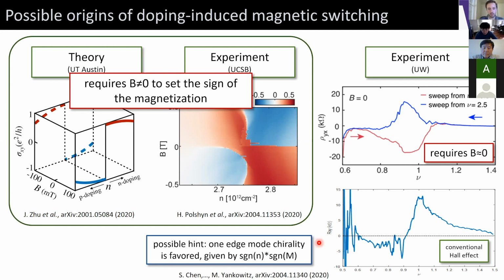And the chirality of the edge mode is the same for both of these cases. When we sweep down from positive doping, we're sweeping from electrons with a positive Hall coefficient, and it chooses a positive magnetization. And when we sweep up from low carrier density, we're sweeping holes, which have the opposite sign, and get the opposite sign of the magnetization. So if you work out the sign, this actually favors, I think, one chirality of the edge mode. So maybe some sort of inhomogeneity in the edges of the sample is responsible for this switching. But nevertheless, this is exciting if it can be reproduced reliably, because realizing doping-induced switching of magnetic ordering is something that's highly desirable in the spintronics community.